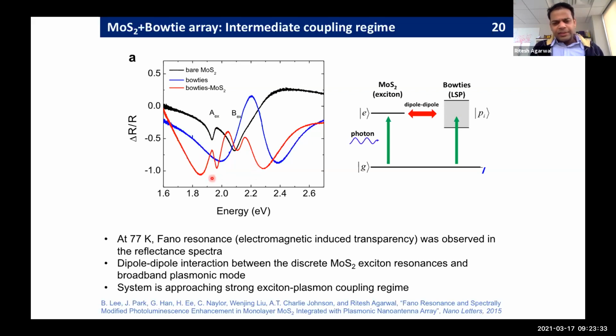And these are asymmetric modes. Clearly, the line shapes were changing. This was telling us something, and this got me excited. This was published in 2015, so this was a long time back. Clearly, a two-dimensional material combined with a plasmonic cavity, which has all the issues of a plasmonic cavity, strong damping, still one can start to change the line shapes of the material. Okay, so this was not strong coupling, but it was approaching strong coupling.